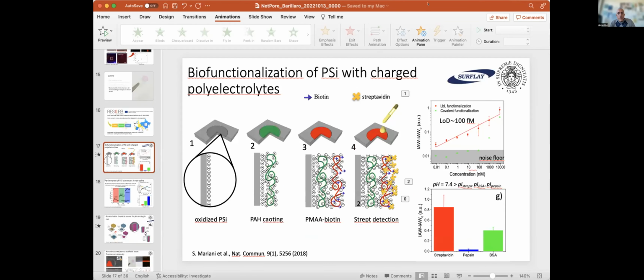The advantage of using this polyelectrolyte is that you can really control the coverage in a much better way. For example, this polyelectrolyte has not been used before for sensing, but it has been largely used for drug delivery for silicon nanoparticles. So you can really increase the amount of bioreceptor you can get inside the porous layer.